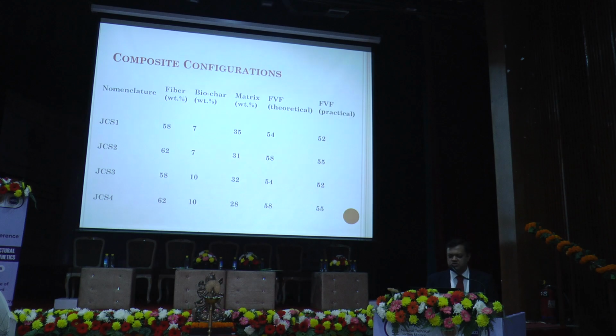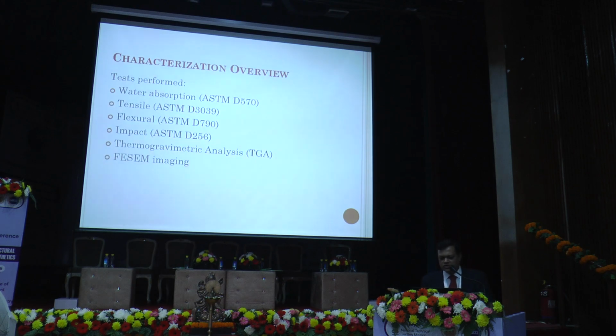This is all about the specification of composites. This is part of the research. I have shown only 4 composites, but in fact we prepared almost 30 with different variability, with different weight fractions. You can get a fiber volume fraction of 52 and 55%, which is quite good. These are the different characterization techniques followed for water absorption, tensile, flexural and impact properties. We also went for TGA and SEM imaging after the testing.